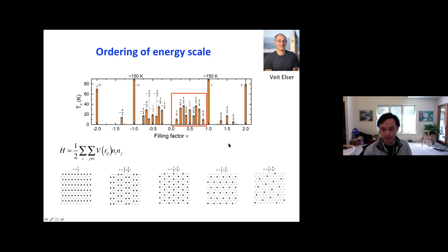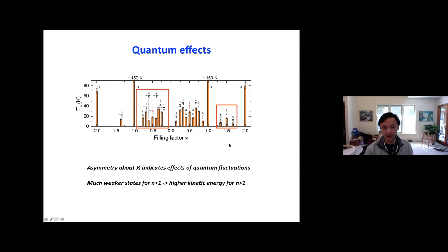Well, there are some other, more weird things going on. For instance, there's a little bit of asymmetry on the hole side, which we think is actually a reflection of the quantum effect, the ignorance of the T in the model. And also between filling factor 1 and 2, you can see that the 3/2 state actually has higher TC compared to the 4/3 and 5/3 states, which is totally the opposite of what's happening between filling factor 0 and 1. So we believe that these are signatures of the fact that we have to include T in a more sophisticated theoretical model of the system. But we are not entirely sure at this point.